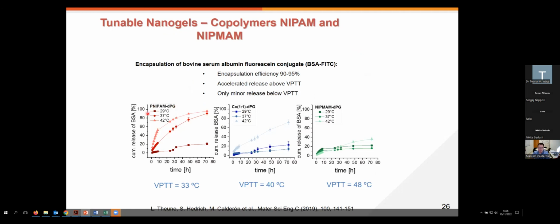We could see that only on those cases that we work with this on the temperatures that cross the transition temperature, we have a very quantitative release of the protein, but when we are below the transition temperature, this release is hindered, and it's pretty much what we expected to see.